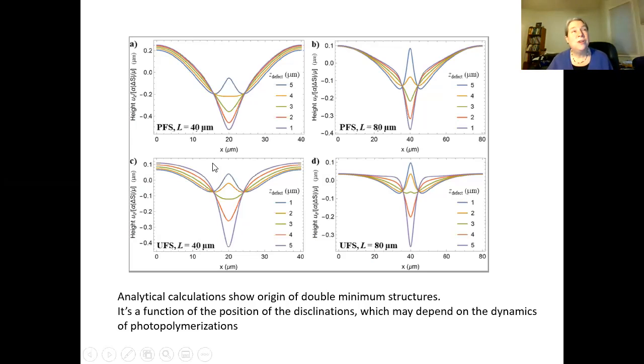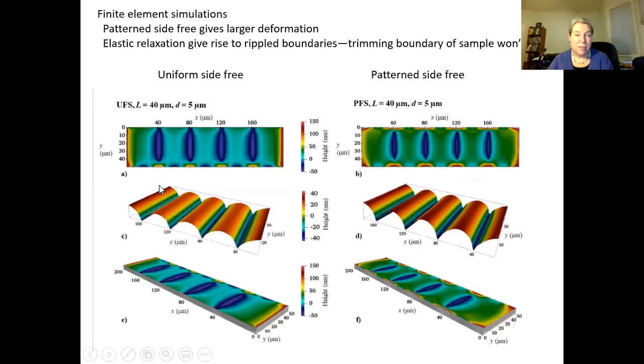And then it turns out, well, you would think the position of the disclination just depends on the liquid crystal. What are the Frank constants? What are the bounding surfaces? But the issue is when you're photopolymerizing it, the dynamics of photopolymerization might depend on how close the UV light is and how long it's on, so you could end up with the disclination in different places. So even when they tried to repeat the experiment, sometimes it didn't come out exactly the same. And then of course we wanted to do the full 3D picture. So here is what you get if the uniform side is free, and if the pattern side is free. And here's some things that we learned.